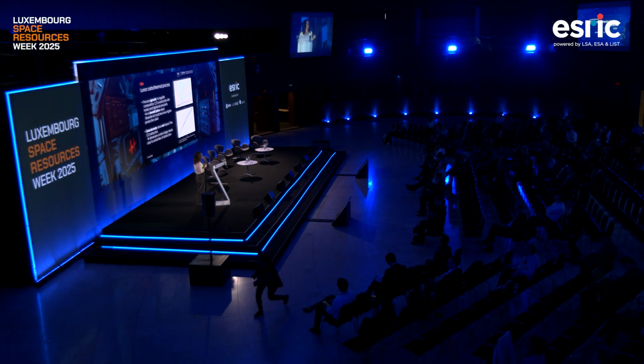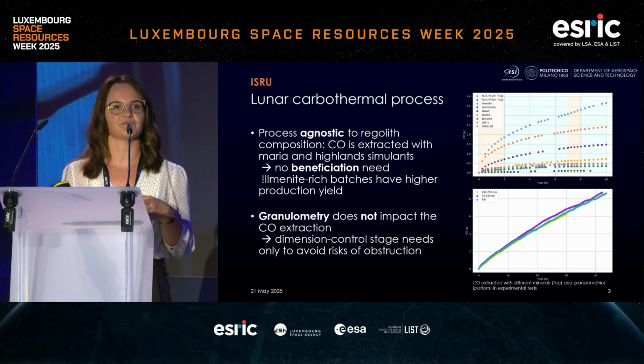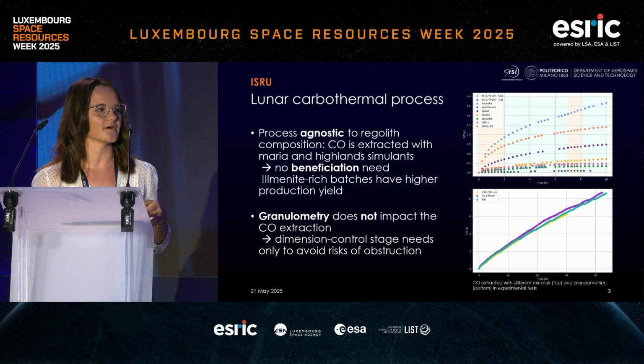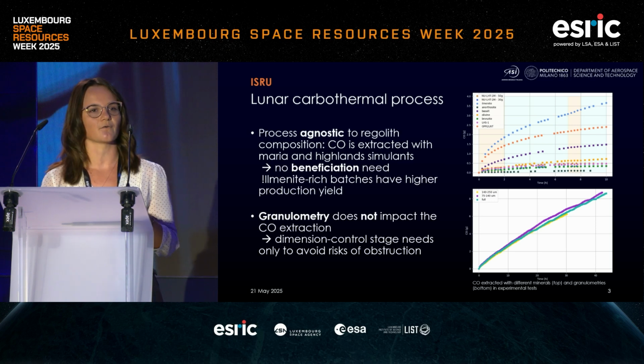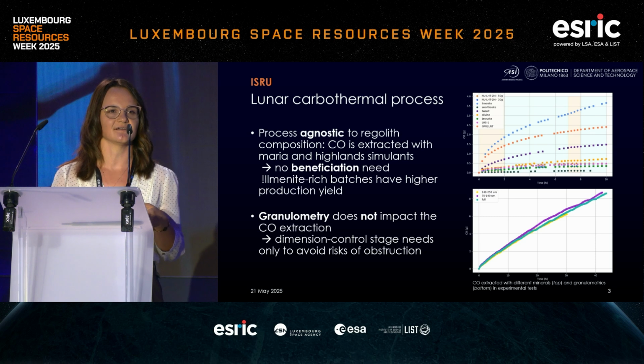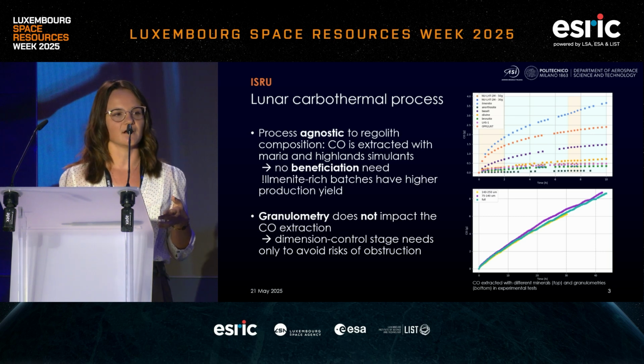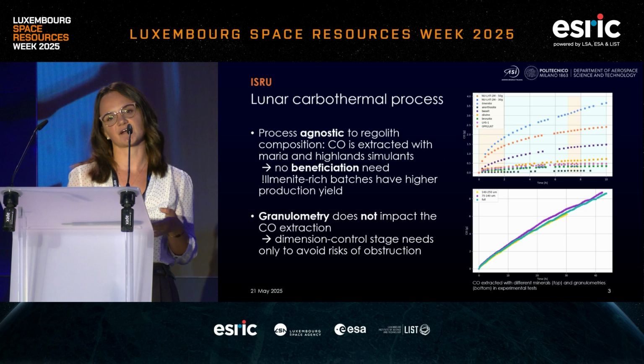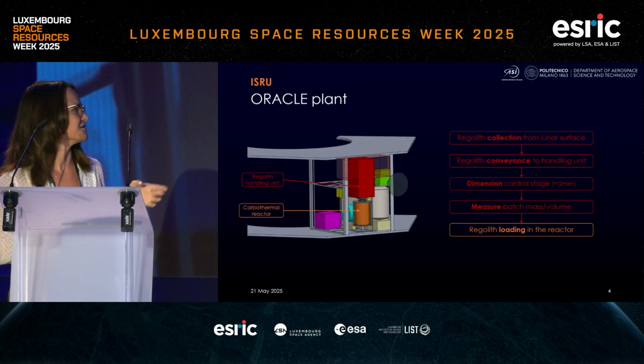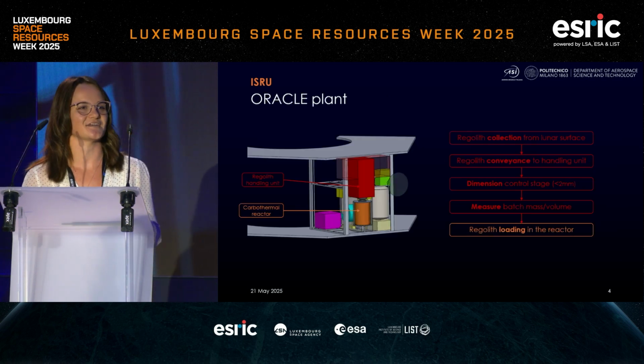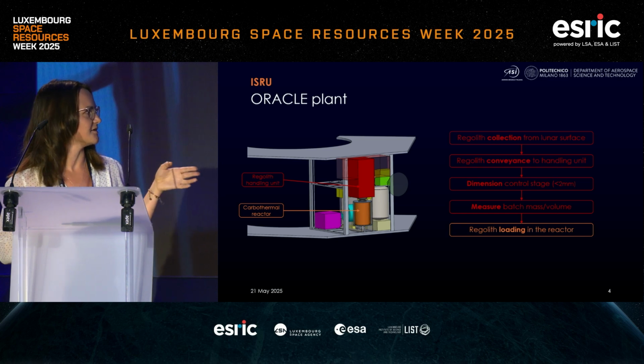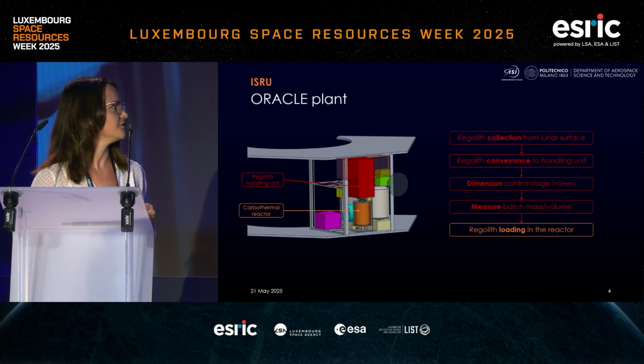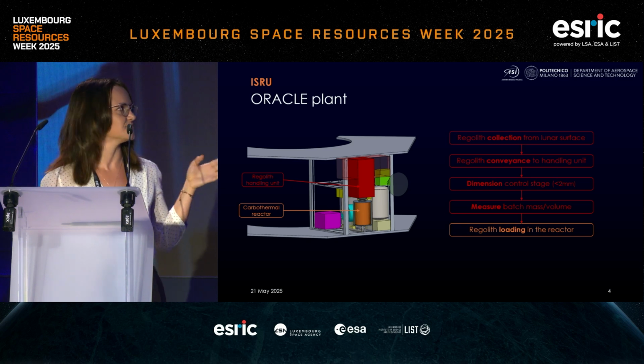We also won't need a grain dimension control stage for process purposes, because as you can see from the plot at the bottom, we tested different particle size distributions for our process and the outputs were quite similar. So we will need a grain dimension control stage just to avoid any risk of obstruction of our plant. This is a very preliminary configuration idea of the lunar plant. And in red is the whole regolith handling unit that will manage the regolith up to the loading inside the reactor.